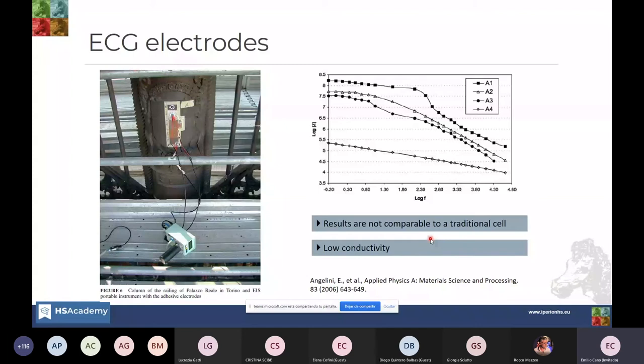The problem is that these results are not comparable to a traditional cell, so the interpretation is, let's say, quite tricky. It is more than usual, and anybody that has done impedance, looking at this result, would say that there are some inflection points that are very strange and probably difficult to understand. This is basically due to the low conductivity of